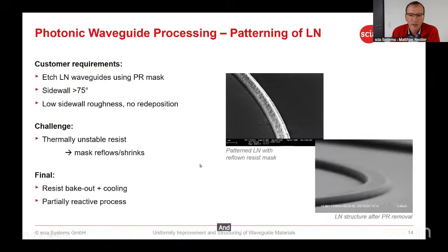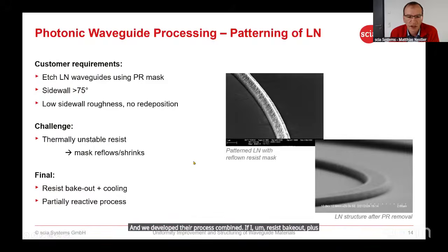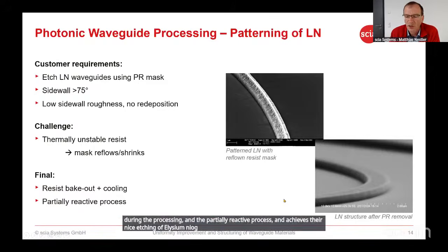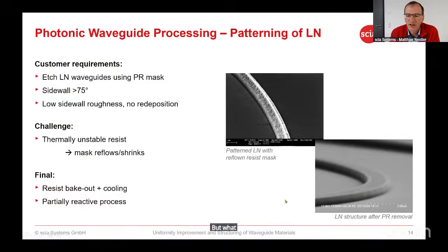And we developed a process combining resist bake-out plus a much improved cooling during the processing and a partially reactive process, and achieved there a nice etching of a lithium niobate structure, what you can see here in the SEM picture on the lower right side.